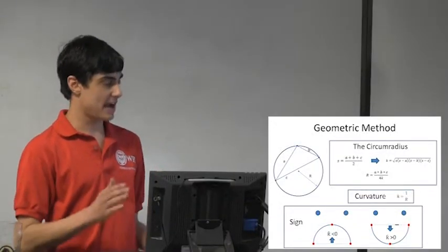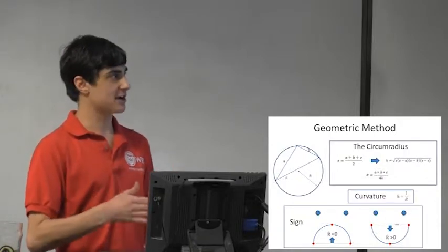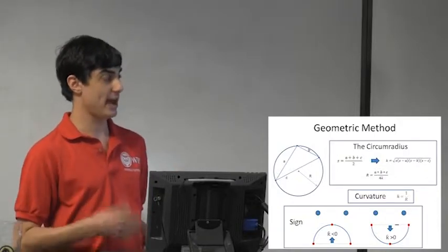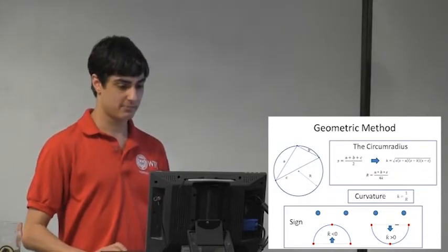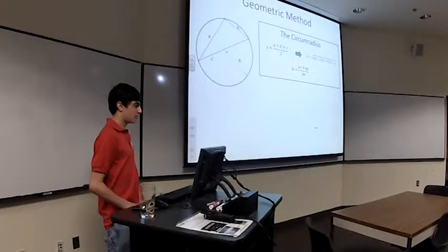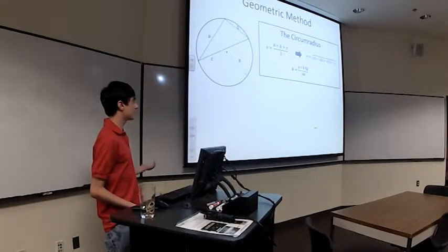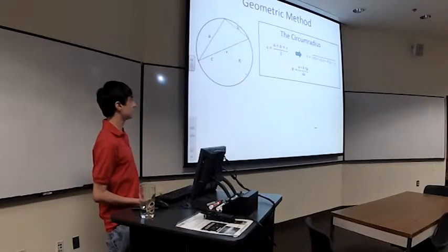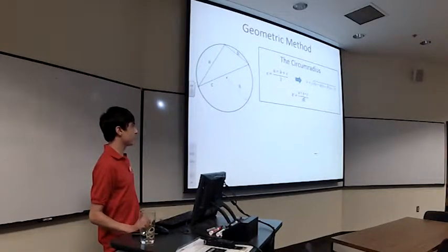We define the area, the distance in the x direction between the first and the last point, as the scale of the measurement. So as we move forward, keep that in mind. Like I mentioned, the method that we've been using is a geometric method. It's based on Heron's formula. You get the area of the triangle from that, and you can calculate the circumradius from that.